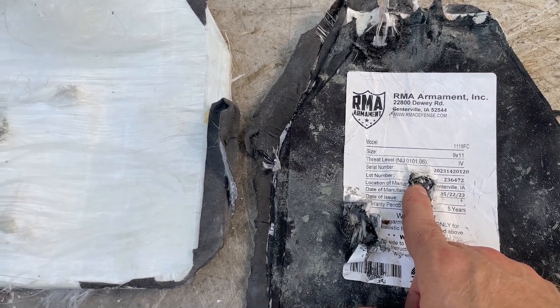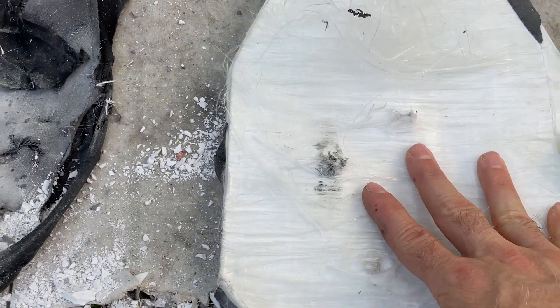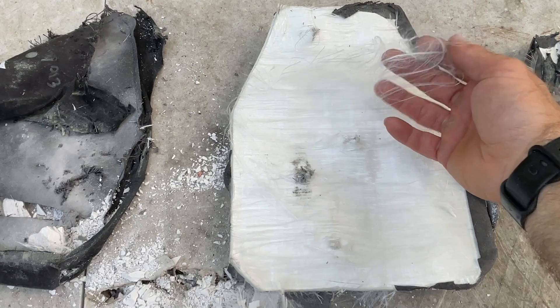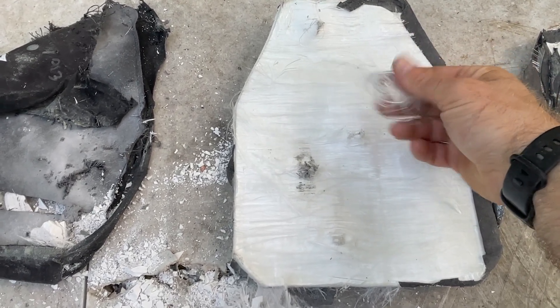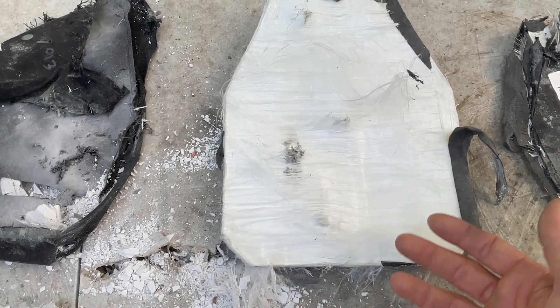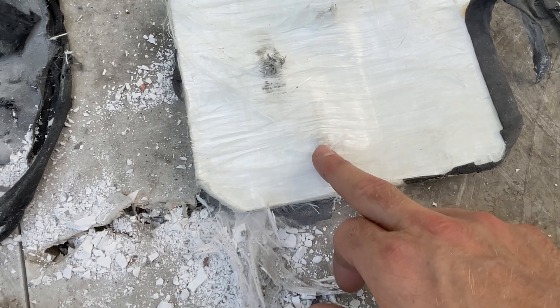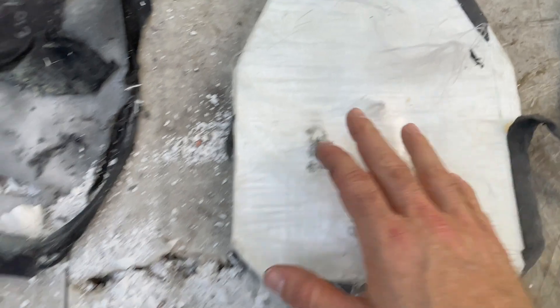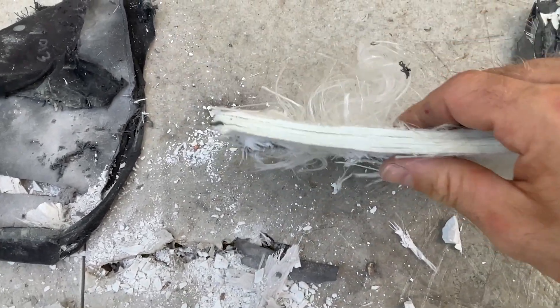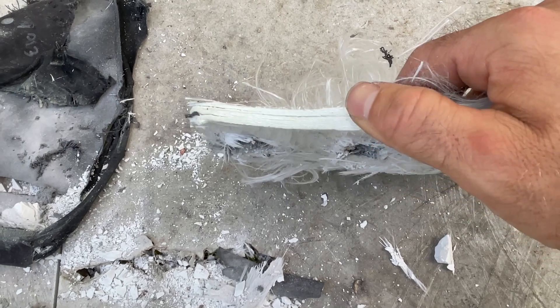Now for the teardown — let's see what our 1118 female cut plate is made out of. Confirmed only penetrations were the M193, the M855A1 shot number two on the first string, and the 7N6M that was literally placed on top of a compromised area. Here is our backing material — it does appear pressed. It looks like the same material they are using in the 1155 — more of that coarse, gritty, fiberglass-like material, not polyethylene. I think it's called e-glass. I double-checked the second hit of M855A1 and it did not penetrate, though the penetrating core did get pretty deep.